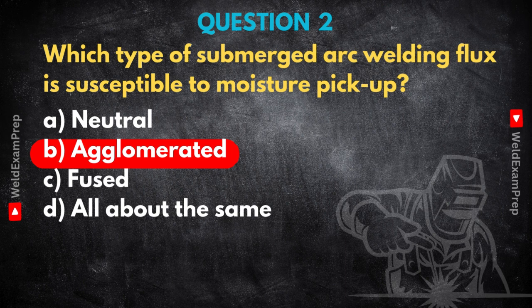And site challenges, plenty of those. Storage might be poor, maybe high humidity, maybe the redrying ovens aren't working right, or people just leave bags open. Yeah, I can see that. An inspector has to be constantly checking storage areas, oven temps, making sure flux is issued properly, not left lying around. It's a real battle to keep that moisture out and ensure quality. That really highlights how prep is just as vital as the welding itself. Knowing about that manufacturing difference, that vulnerability, that's key to stopping defects before they start. Okay, so we've talked prevention, but what about finding defects? That brings us to NDT.